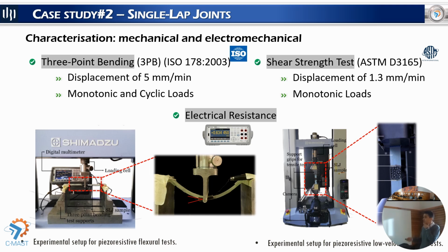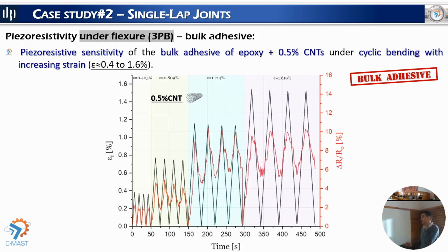During the test, again, we monitor the electrical resistance. Here we have the piezoresistivity of the bulk adhesive. So these results regard the bulk adhesive. We first produced the adhesive doped with carbon nanotubes, and we studied the adhesive first. And here we can see that the adhesive presents a piezoresistivity that was sensitive to the variation of the strain. We increased the level of strain and we measured the electrical resistance variation, and we observed that there is a correspondence between these two signals.